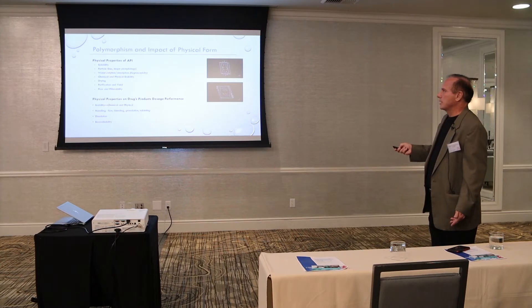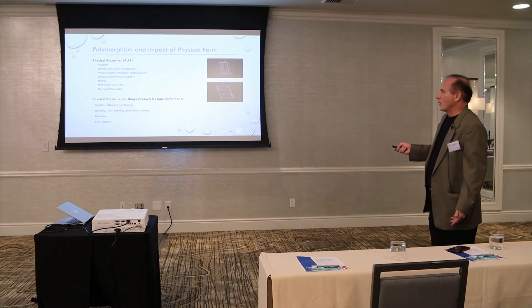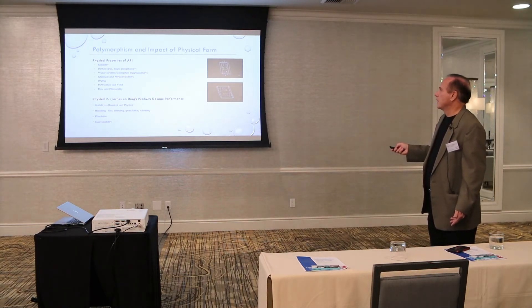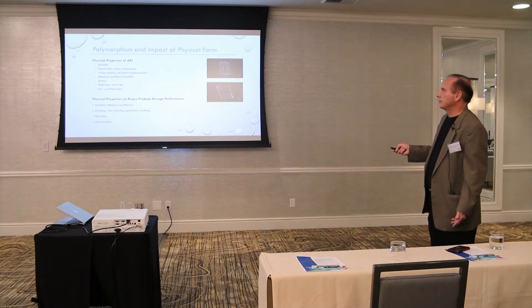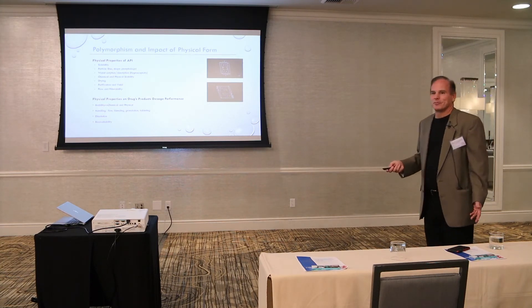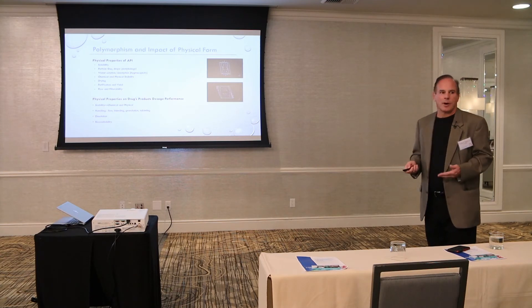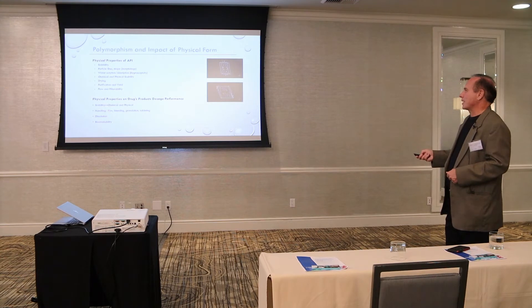Properties affected include solubility, particle size, shape, and morphology; water sorption and desorption, or hygroscopicity; chemical and physical stability — how much the compound degrades in the solid state — and whether it transforms to another solid-state form. Drying properties, purification, and yield are also impacted considerably by the physical form. Flow and filterability are commonly impacted as well. When mixed with excipients, chemical stability can be differentiated — two polymorphs might have quite different chemical stability, which can actually kill projects.